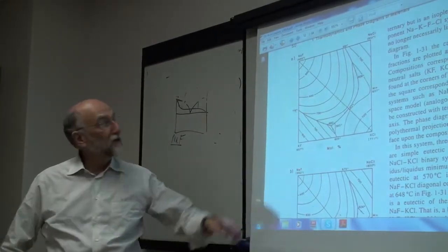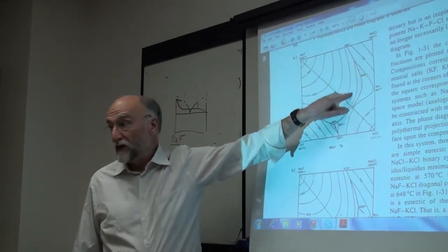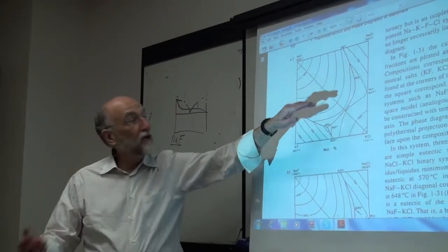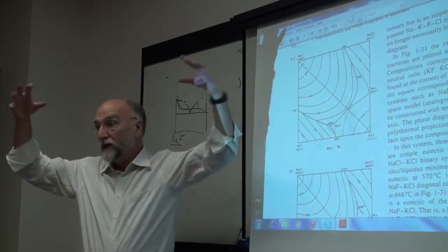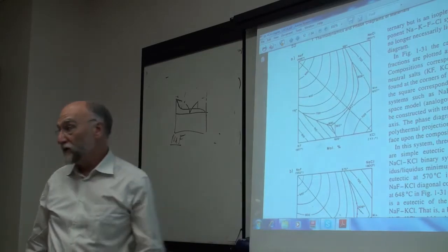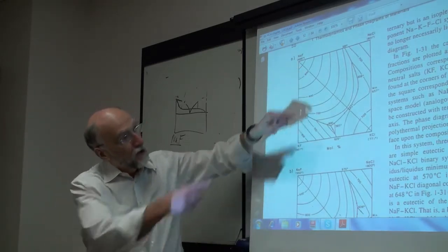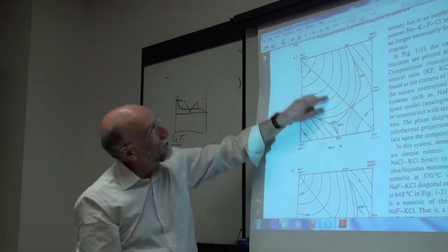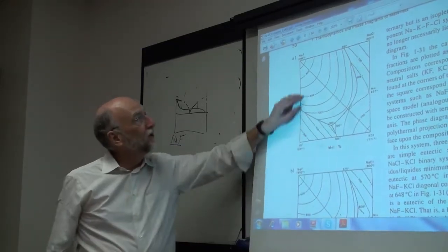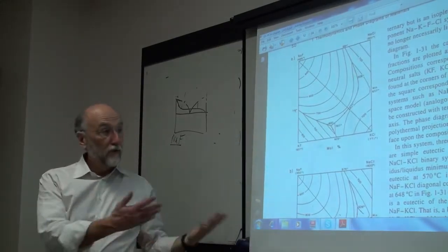I gave you another example. I think it was lithium fluoride KBr, in which you actually had a miscibility gap. If you use the equations I showed you, you get the gap, but it's way too big. It's too wide. It's too high. You overestimate the positive deviations. Okay, so if you use molecules, the bad model with molecules, you don't get any positive deviations, so that's no good. But if you take into account the 2 sublattices, you get the positive deviations for the reasons I stated,